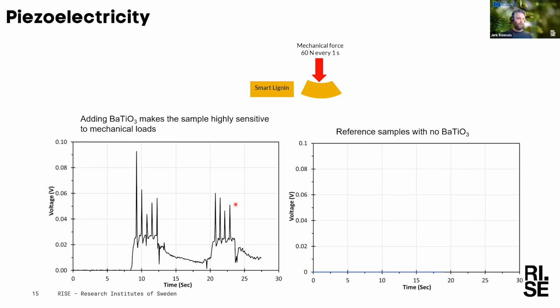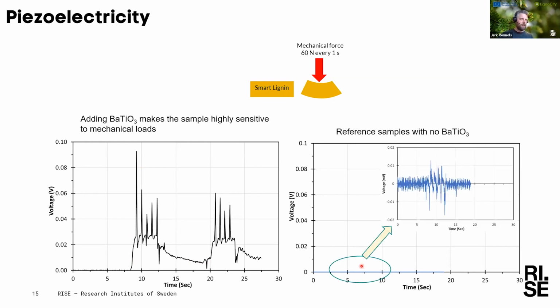We have a reference sample here to the right without any barium titanate, and you can see it's almost flat on the ground. You can see some very faint response just introduced by the machinery itself. But so we succeeded here to make a piezoelectric material by introducing barium titanate.